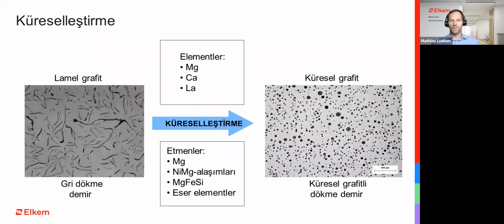Okay, as an introduction, a short glance at the nodularization process. Starting with the base iron on the left side, you can see the flake graphite. We are adding special nodularization agents like magnesium ferrosilicon or others with active elements like magnesium, calcium, or lanthanum. These elements tie up sulfur and oxygen and nodularize the graphite. But be careful, too high an addition rate increases chill and shrinkage tendency and also the tendency to slag formation.